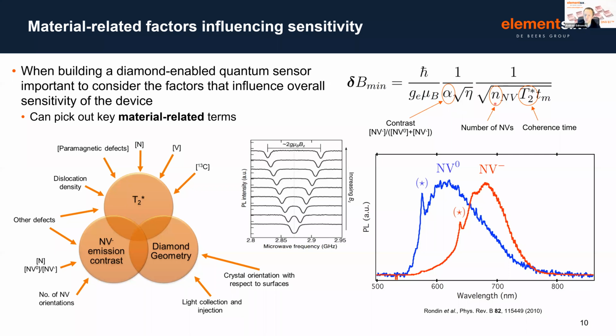So the first one, the most simple one, is simply the number of NVs that we're using in this system. If we use a larger ensemble of NVs, we'll observe more luminescence and a signal is more readily detected. The coherence time is also critical because what we've seen in this schematic shown again in the center of this slide is this idea that we see groups of resonance lines, and it's the sharpness of these resonance lines that's given by the coherence time. So a sharper resonance line makes it easier for us to detect a small change in magnetic field, so a more sensitive device. And then there's the concept of contrast in this device.